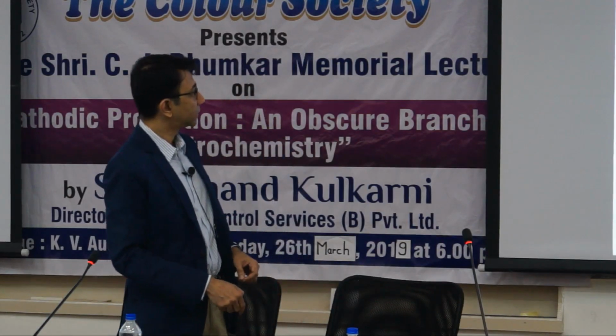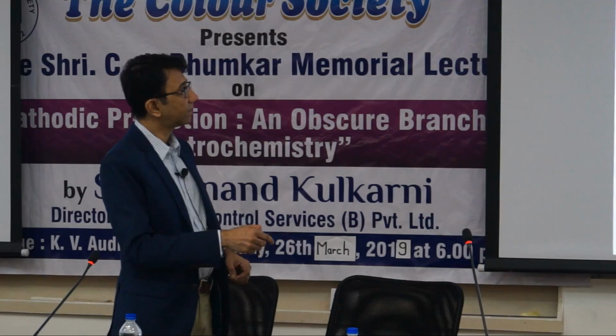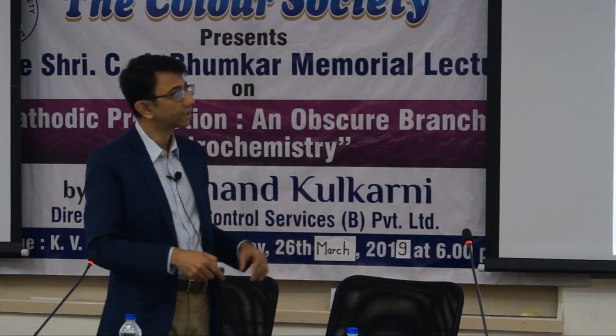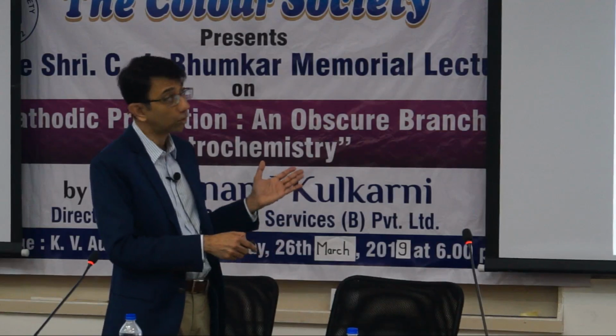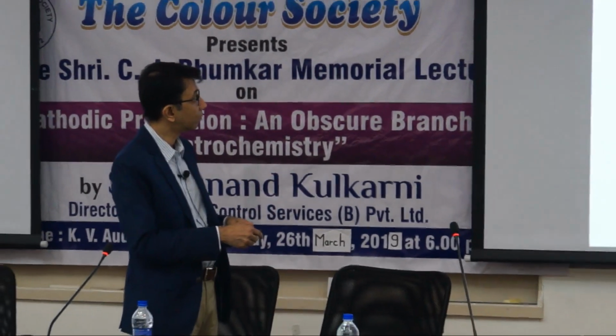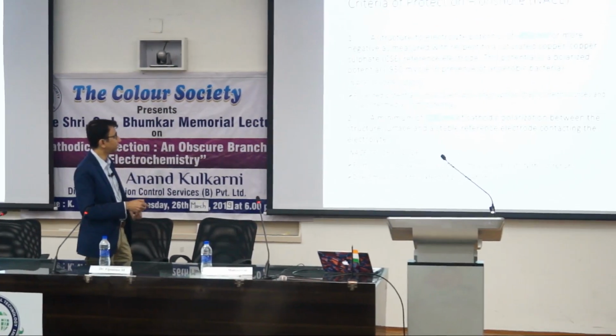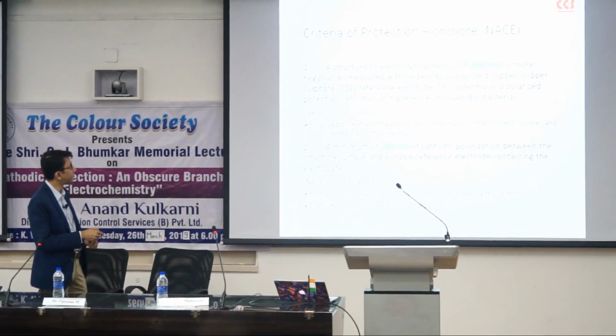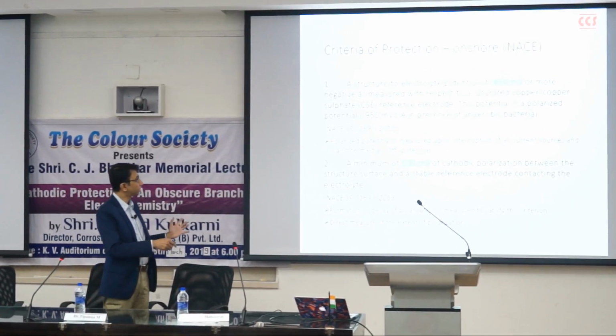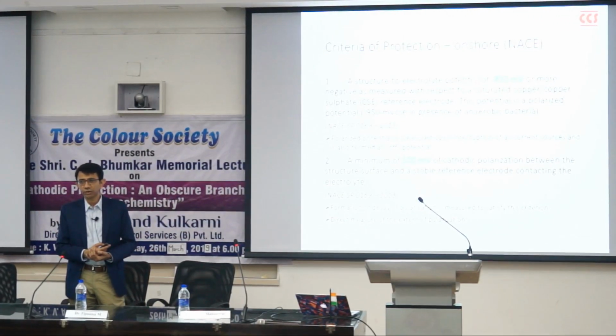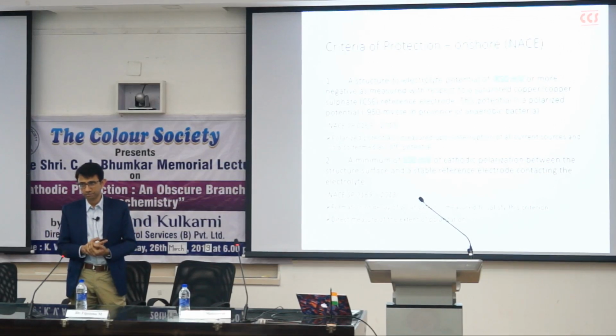These are the criteria of protection. Don't want to go into great details, but this is a kind of a magic number. Green because it's protected, minus 850 millivolts. This is for an onshore pipeline, NACE standard 169 of 2013. And it says if you have a structure to electrolyte potential of minus 850 or more negative measured with respect to a copper sulfate reference electrode, and if this potential is a polarized potential, polarized meaning that this potential is basically measured when there is no current in the circuit. So polarized potential is measured upon interruption of all current sources.